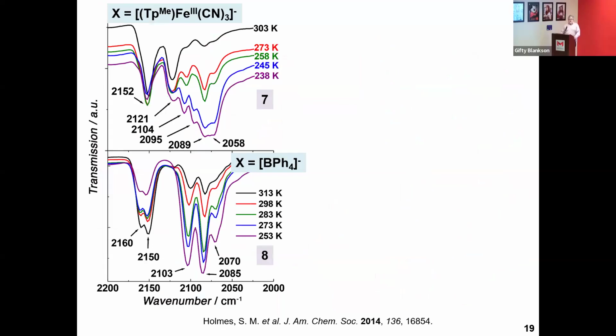All right, complicated infrared spectra, but I thought I'd show you a little bit because hopefully you've seen that before. But infrared spectra is a nice, cheap method to assay whether or not you have electronic changes in your structure. And so we use this to show that at high temperature, we have very high energy stretch. It's mostly dominated by this anion. Very close to room temperature, we see corresponding increases in lower energy absorption, which is due to electron transfer. In the tetraphenyl borate case, you don't have any cyanides to worry about, so it's much easier to understand. High energy stretches initially. Notice I have two now. That's interesting. We thought, hey, maybe we can make things that do electron transfer in 2 steps. Turns out, no, not for this compound. But for others, we can.